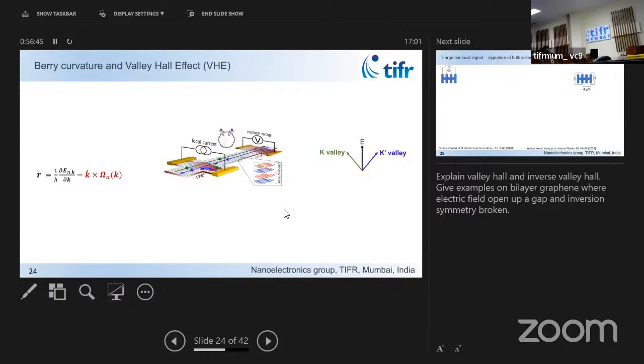So in these systems also this anomalous velocity plays an important role. If you make a device out of a twisted double bilayer, like I showed you, you can actually characterize its Berry curvature. In these experiments, if you send a charge current, because the two valleys have opposite Berry curvature, electrons of one valley, let's say blue, will get deflected to one side because the Berry curvature provides one kind of anomalous velocity, whereas the green, which are electrons belonging to the other valley, will get deflected in the other direction, just because the material has that symmetry. And then in this direction, you get no net charge current, but a current flowing of the valley degree of freedom. It's like saying a net spin current in this direction. The valley degree of freedom is very analogous to the spin degree of freedom. It's much more than that, but it's easy to make that connection.